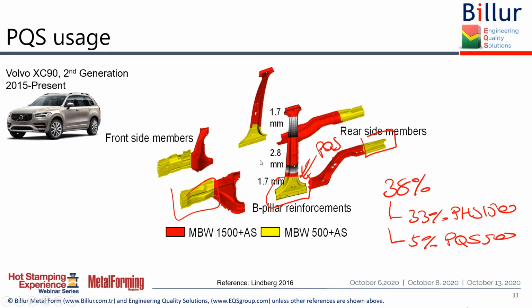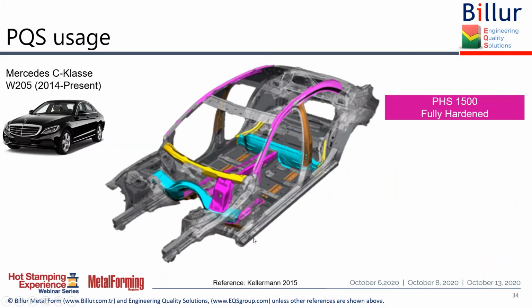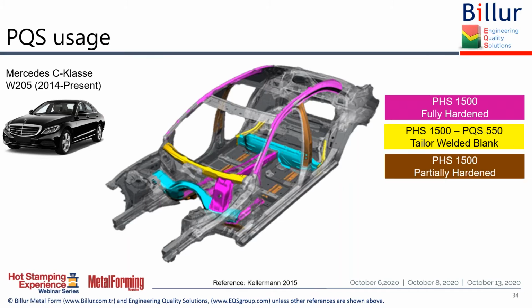But in recent years, we have also seen cars with PQS components. Here we see the C-Class Mercedes. It's still in production, the latest generation from 2014. The pink colored parts, like the A pillar all the way to the back, are PHS 1500 and fully hardened. We also have several components in the floor and also for the steering wheel. Then we have the yellow parts, like the rear rail, and I think this is called cowl part. It's a tailor welded blank with PHS 1500 and PQS 550. Then we have the B pillar, which is partially hardened with soft zones PHS 1500.